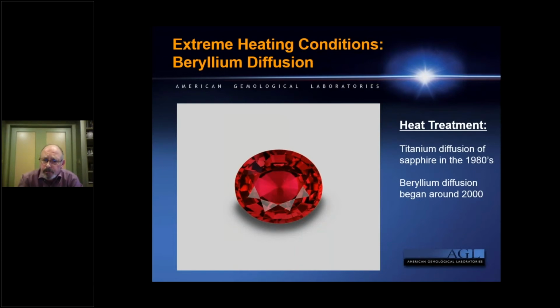And so I want to compare it to the titanium diffusion, which we started to see in the 1980s. For those of you who are familiar with the titanium diffusion, this is a shallow penetration. So one of the best and easiest ways to recognize this is by putting the stone in immersion over a diffused light source. And you'll see a patchwork of coloration that's following the faceting.